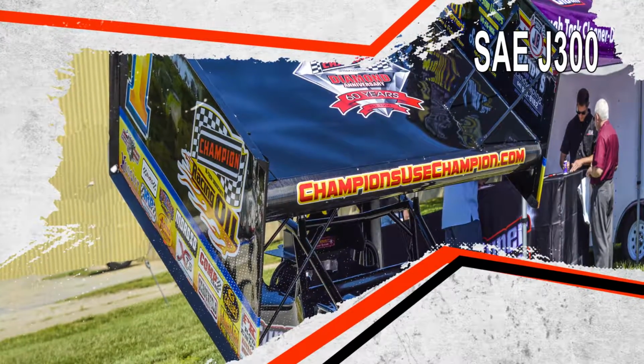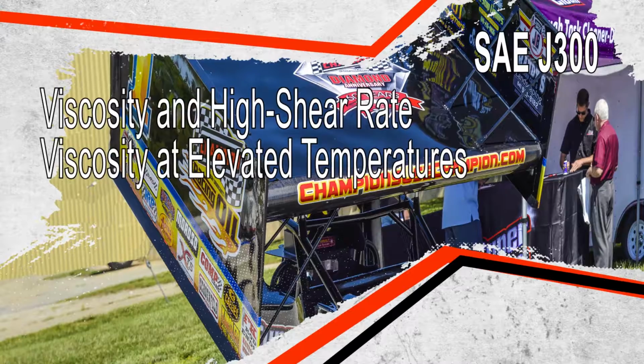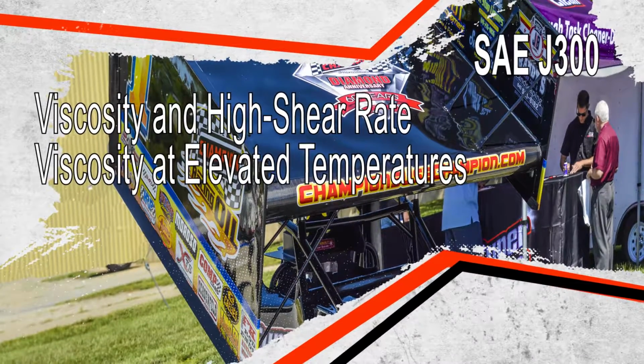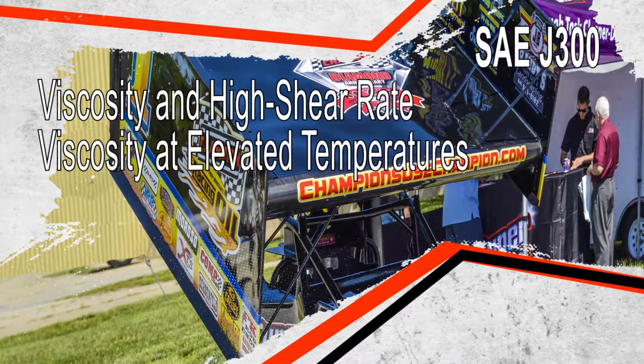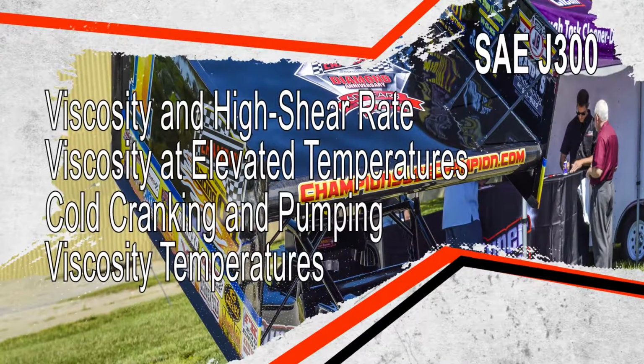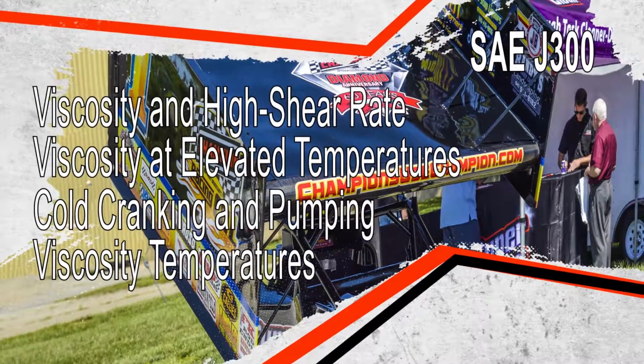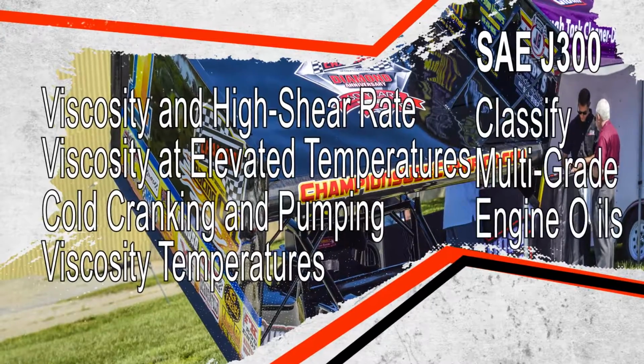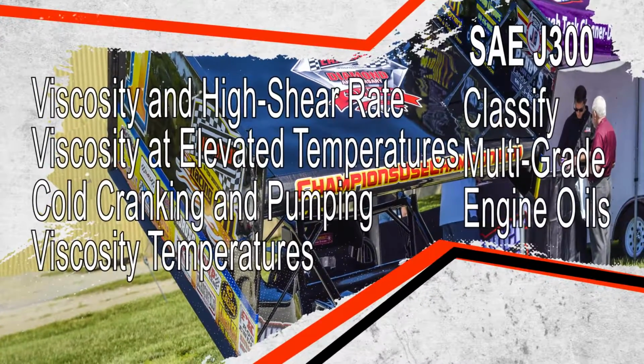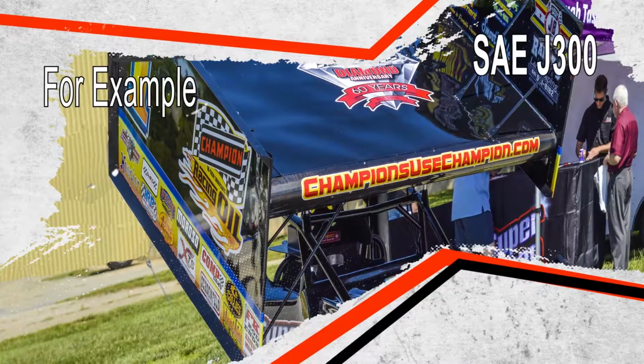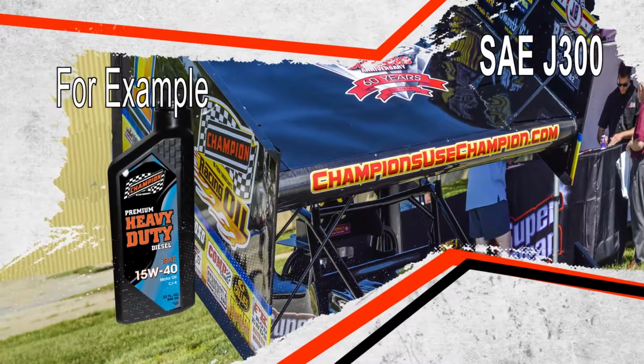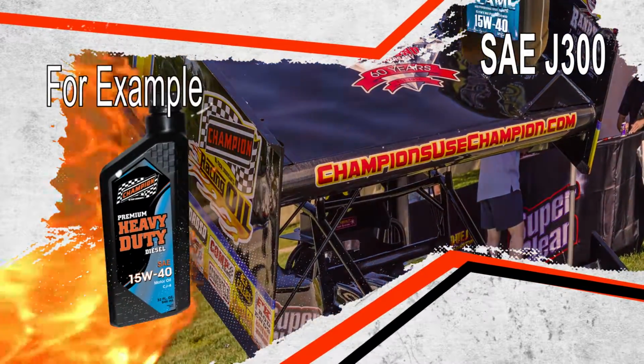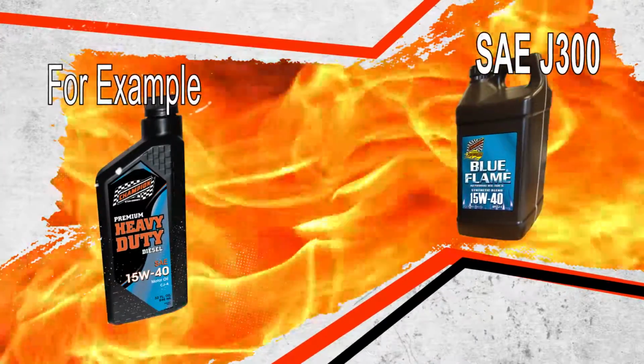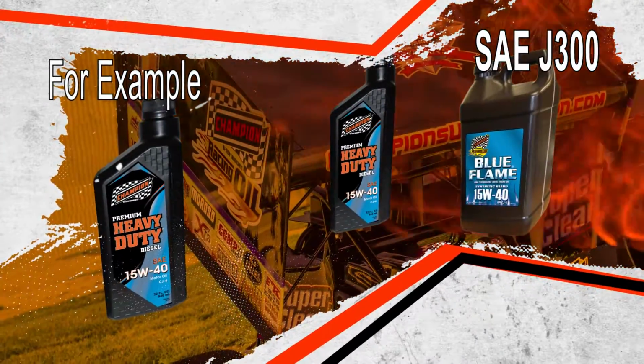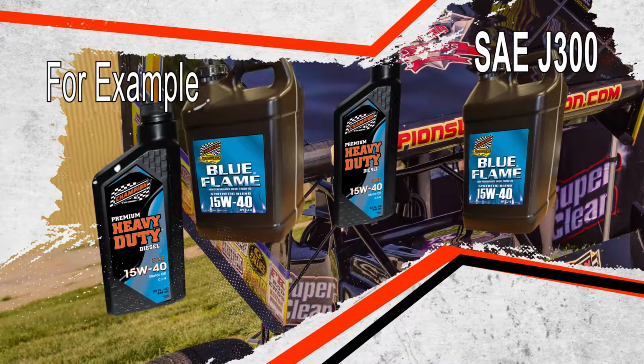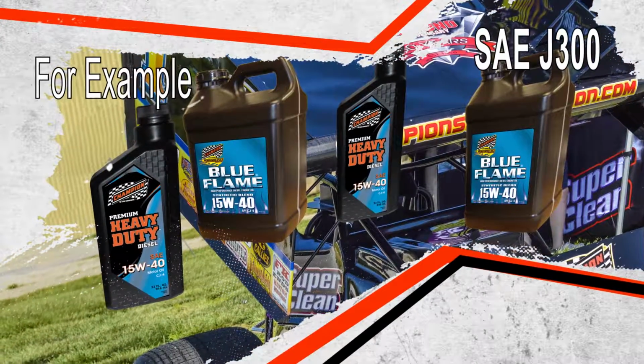SAE J300 classifies oils by their viscosity and high shear rate viscosity at elevated temperatures, but also has a separate classification for cold cranking and pumping viscosity temperatures. These systems are used together to classify multi-grade engine oils. For example, an SAE 15W40 has a viscosity at 212 degrees Fahrenheit of between 12.5 and 16.3 centistokes and must pump at -13 degrees Fahrenheit and must crank at -4 degrees Fahrenheit.